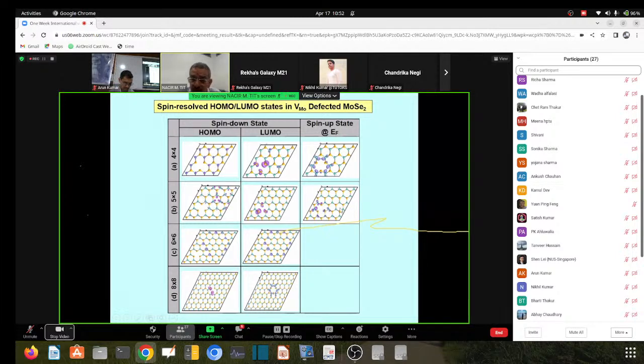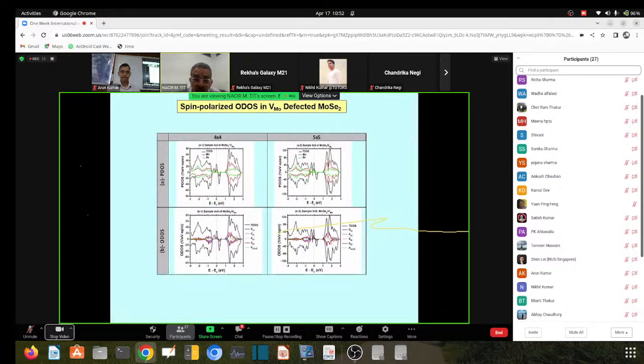Each vacancy, as you can see, we have periodic boundary conditions, so it has six neighboring vacancies because of the triangular lattice. And there is disappearance of metallicity after 5x5.